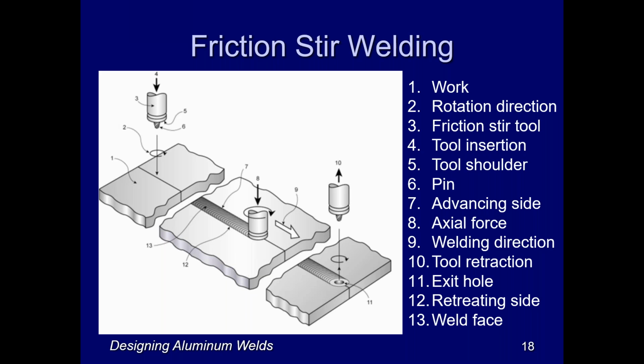Now, there can be an exit hole at the point of withdrawal, and that can be an issue sometimes. Sometimes you need to use a runoff tab, as it's called, or you need to have the exit hole in a low stressed area of the part, or maybe you need to MIG weld a plug in that exit hole, but there are various ways to address that. There are also more complicated friction stir welding processes that eliminate exit holes, but you get the idea.